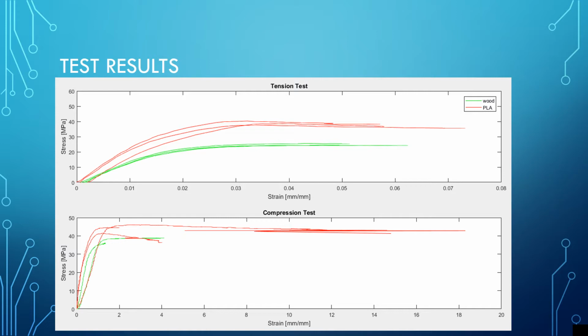It should also be noted that the average width and depth of the dog bone test specimens made of wood filament were different from the dog bones made from PLA filament. The average width and depth of a dog bone made from wood filament is about 6.37 millimeters and 6.06 millimeters respectively. The average width and depth of a dog bone made from PLA filament is 6.07 millimeters and 6.15 millimeters respectively. Both sets of dog bones were printed using the same G code, so it is unclear why their dimensions are slightly off. Because these testing specimens have different average cross-sections, the results of the tension tests may be affected.